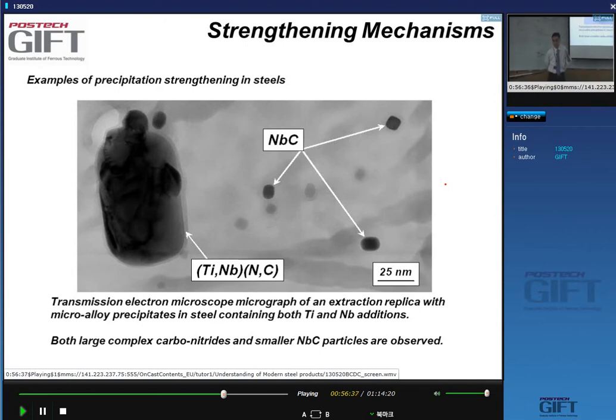So any particle that is larger, because of the fact that R is in the denominator, any larger particles will give you very low strengthening effects. Yeah? So it's important to control the size of precipitates if you want any strengthening effect.